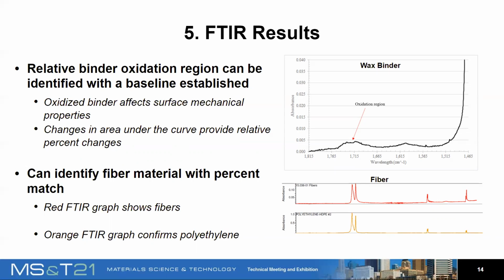The graph below shows how the material can also be identified. The red spectrum is the sample fiber spectra, while the orange spectrum below it is the spectra of polyethylene. And you can see the similarities between the two spectra. And from that, we can determine how similar our unknown sample fiber is just by comparing it to the libraries or just comparing it to existing spectra that we already have.